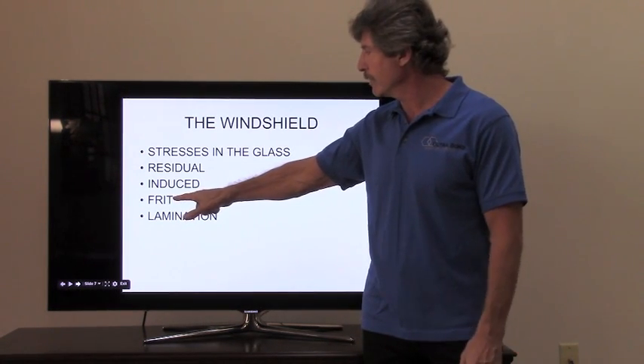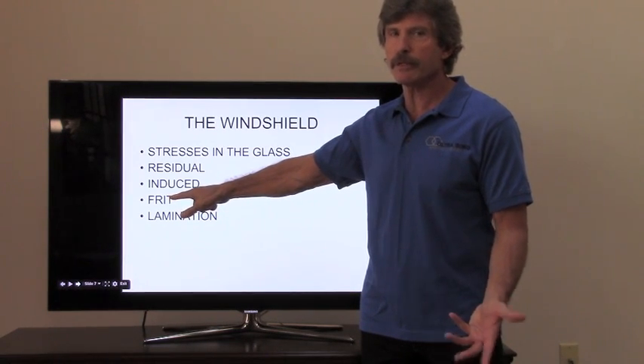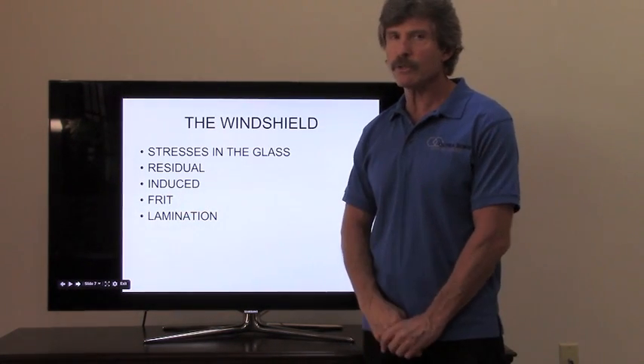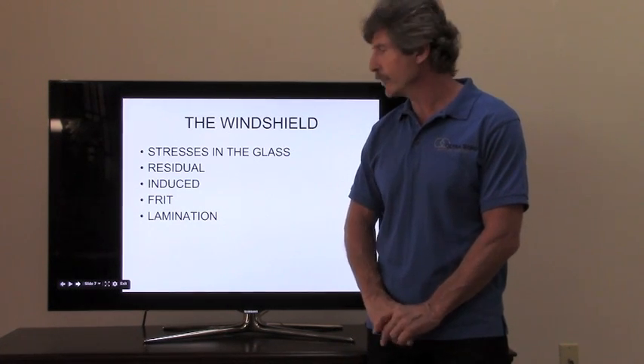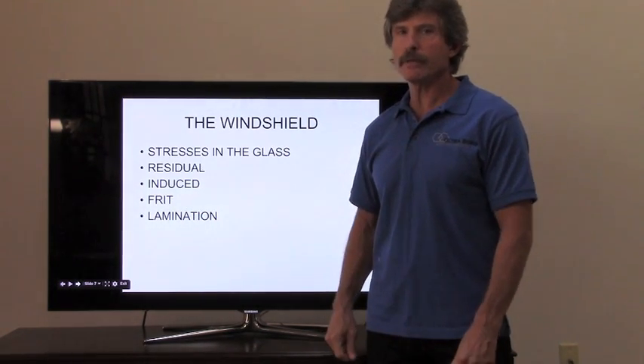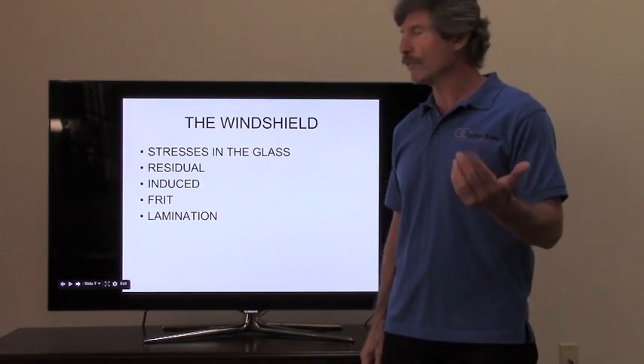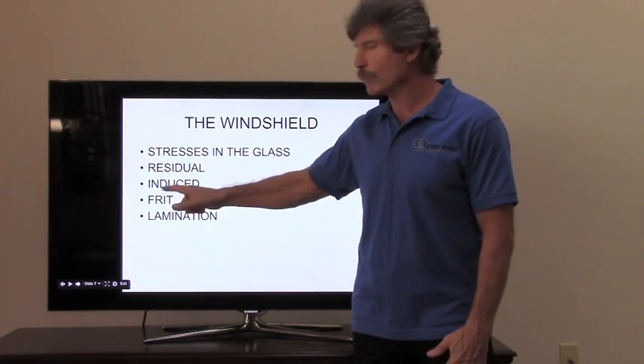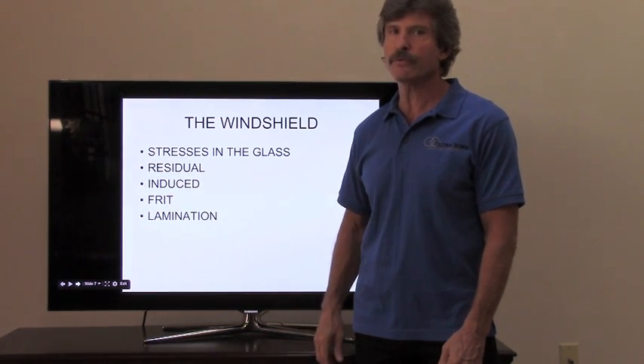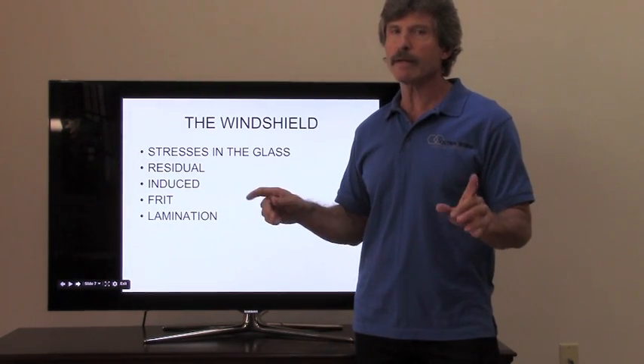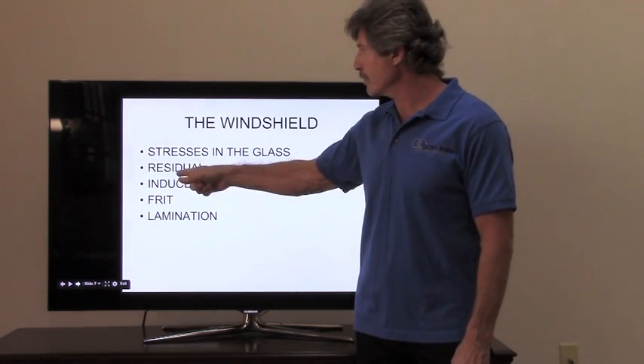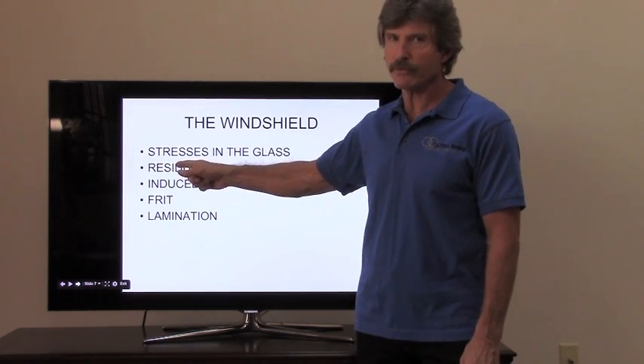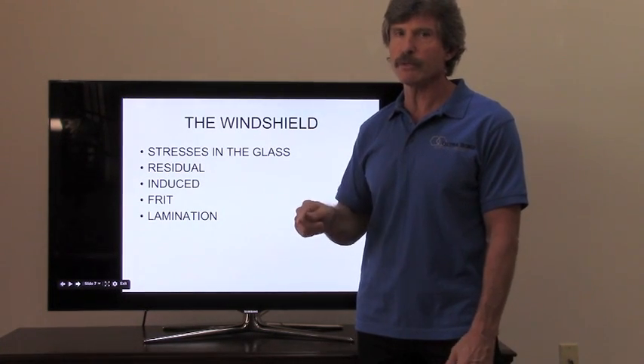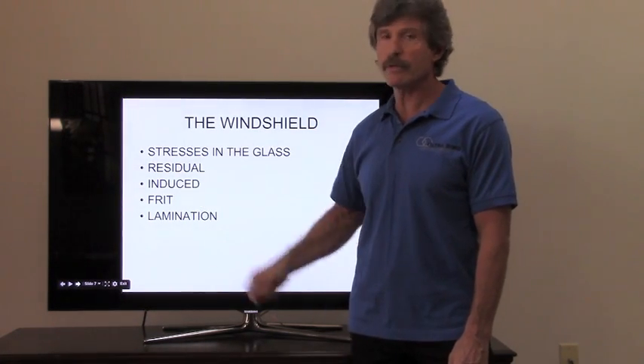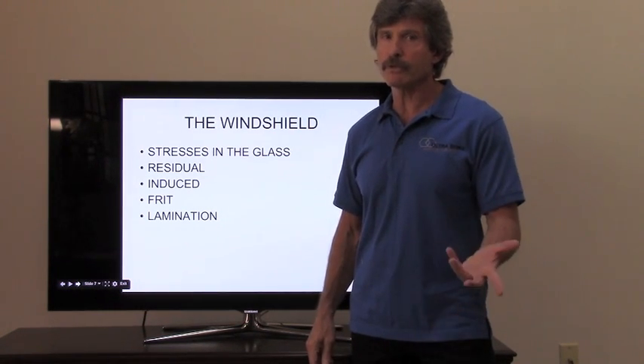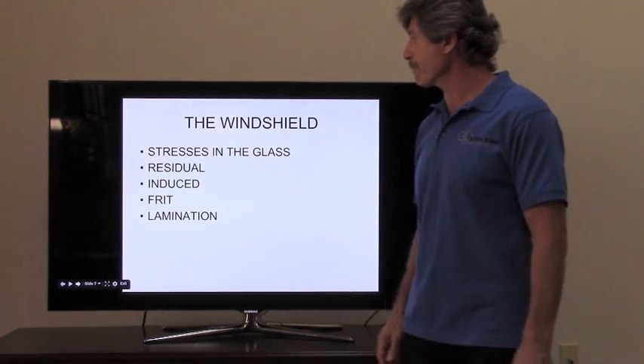Any engineer that designed this has actually contributed to making windshields the number one insurance claim in the United States. The frit is baked on into the glass when it goes into the furnace. And putting the frit on weakens that area by 40%. So you have already weakened that area by putting the frit on, and then you throw the residual stress on there from the annealing process, and you've got a mess at the edge of the windshield, the first few inches, and then where the frit is. That's why you're going to notice most of your cracks have an impact in the frit.